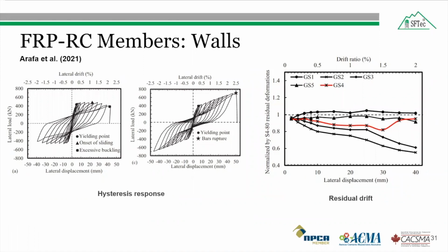Extending the GFRP bars, either arranged diagonally or vertically, along the wall height was necessary to ensure their effectiveness in controlling damage. Further, they satisfy the demand of ductile recoverable performance up to a maximum drift of 2%, which is recommended by ASCE 41. The residual drift of the wall with vertical or diagonally arranged GFRP bars was low compared to the wall reinforced with steel bars. As you can see in this figure, the residual drift of the shear wall reinforced with GFRP bars in the diagonal way was much lower. You can also see from the hysteresis response that the residual drift is very low compared to the specimen reinforced with steel bars.